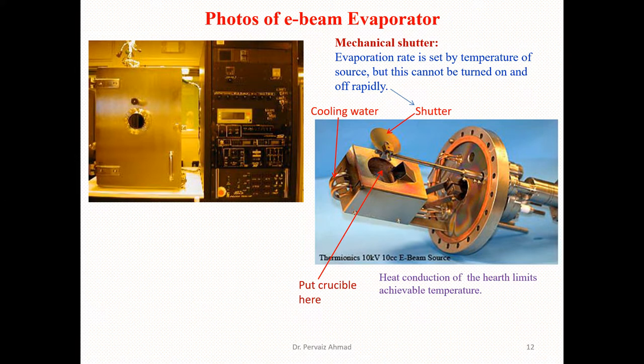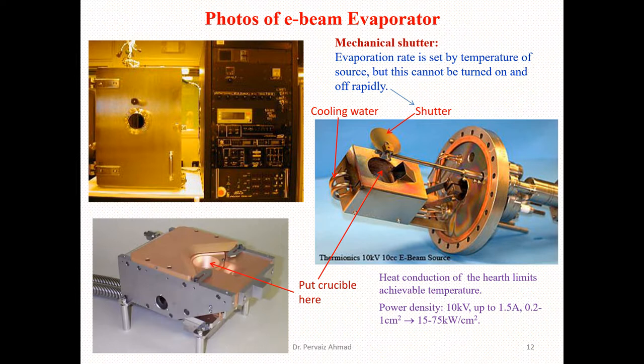The achievable temperature and power density in this setup: the voltage goes up to 10,000 volts at up to 1.5 amperes, over an area of 0.2 to 1 square centimeter, giving a power density of approximately 15 to 75 kilowatts per square centimeter.